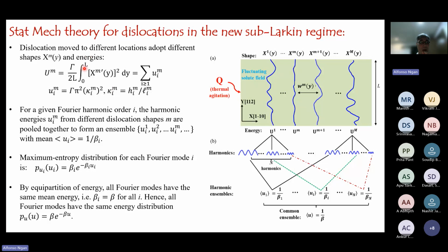And then if you look at this dislocation moving to different positions on the slip plane, they have different shapes. And then you can do Fourier series analysis on each of these shapes, and then we can collect the harmonic energies to form ensembles. By equipartition of energy, each ensemble should have the same mean energy, and therefore the entire collection of harmonics should have only one beta because of equipartition of energy.